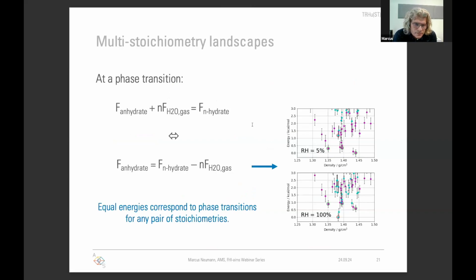So I have to say a couple of words on how we calculate multi-stoichiometry landscapes. So landscapes, how do we compare hydrates to anhydrates? And here it's important to realize that every phase transition between two crystals, so anhydrate-anhydrate or anhydrate-hydrate, is actually a measurement of a free energy, because by definition, at the phase transition, the free energy difference is 0. And what this means is that if we, for instance, compare an anhydrate to a monohydrate, and so for that case, N on this slide would be equal to 1, then the free energy of the anhydrate plus the free energy of one water molecule in the gas phase must be equal to the free energy of the monohydrate, always normalized to one molecule. So that's how we calculate phase transitions.